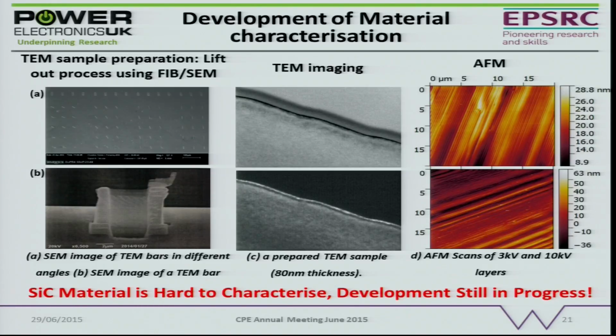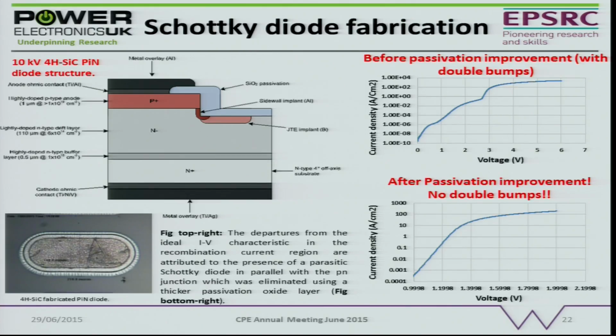looking through some of the epi layers that we've grown, and of course we've got AFM to look at the surface profile as well. That's quite challenging. We've also been making structures using some of the epi layers that we've grown to try and evaluate the quality of those epi layers in real devices. So we made some pin diodes. We made this type of structure. There's one there.